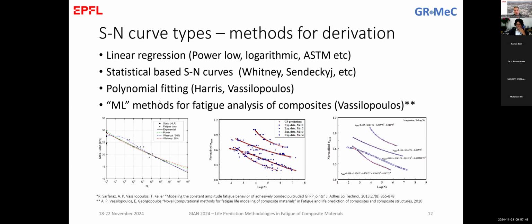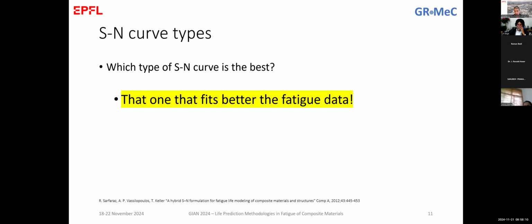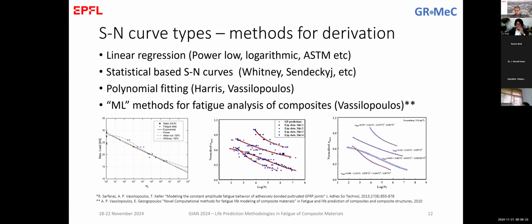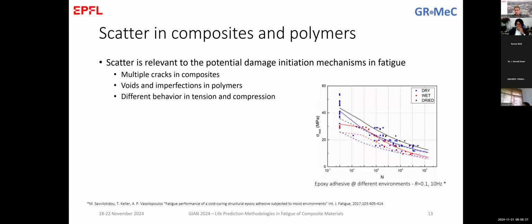So what is visible in these plots here is that any selected method, whatever the type, can be potentially useful and valid for fitting the experimental behavior of composite materials. So coming back to this, the interpretation is that there is no best SN curve in reality. The best one is the one that fits your data best. We discussed yesterday that we have scatter in composites. And if you remember, we said that in composites, experience shows that a decade of life, so between 10^3, for example, and 10^4, is a scatter that is acceptable.